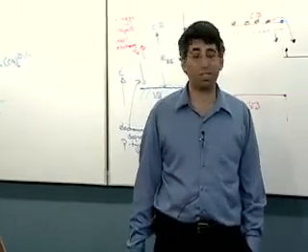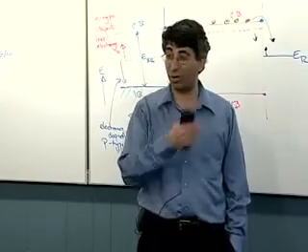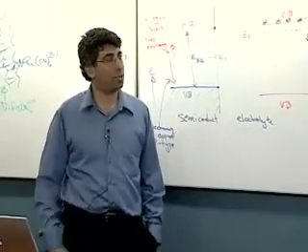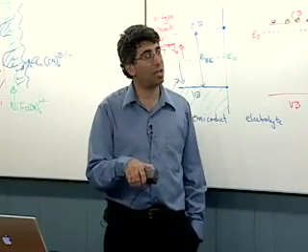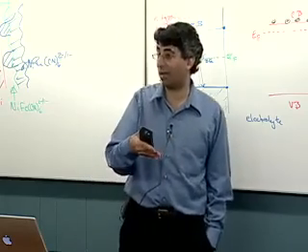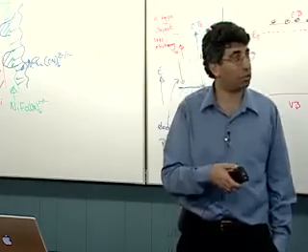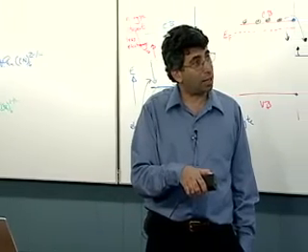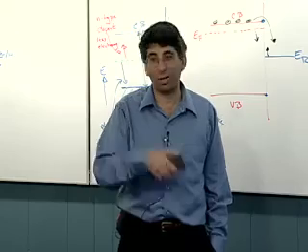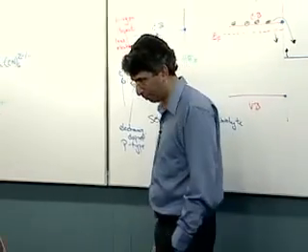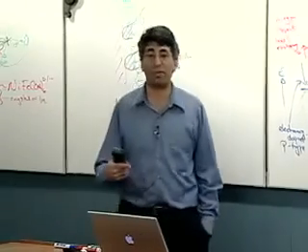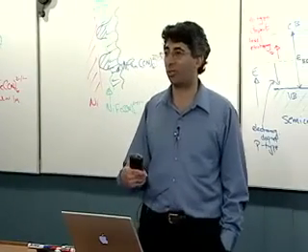Another way you might do this is play with the charge transfer kinetics at the interface, which the Lewis group has specialized in, and tweak that interface either by changing the nature of the semiconductor at the surface or by chemically modifying the interface or throwing in an appropriate solution redox couple so that you can get the rate constants for what you want to be large and the decomposition rate constants to be small. Typically, where people have been successful in doing this, they've had to shut off the rate constants for oxidation of water also to do that.